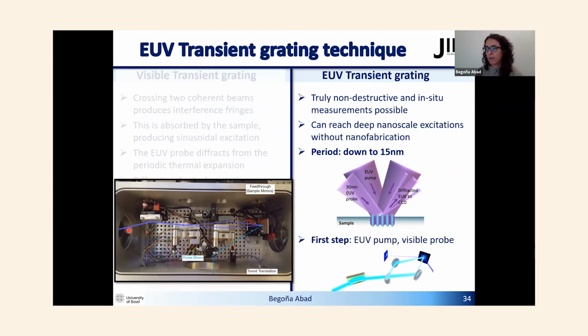This is the vacuum chamber, and we have a toroidal mirror that is able to focus our EUV light onto a mirror that splits the beam onto 2 mirrors, and then these 2 mirrors recombine the beam on the sample. So these 2 beams are able to excite and create this sinusoidal pattern, and then with another beam, we were able to probe the dynamics with a visible probe. So the next step is moving from this visible probe to fully EUV to be able to access these really small periods.